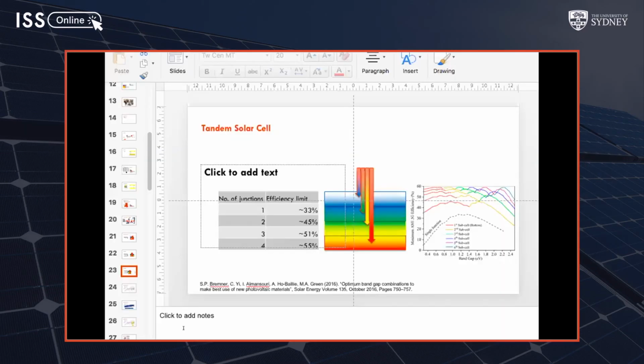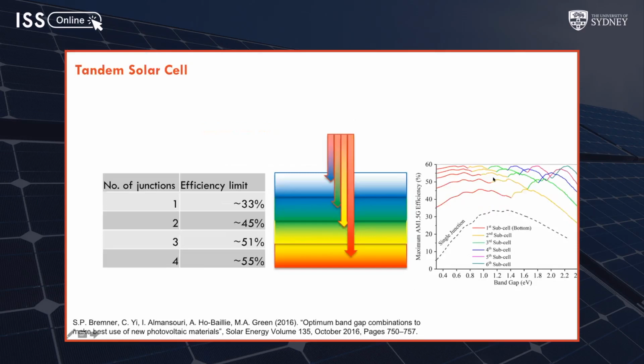Yeah, so if you remember, I showed that diagram where you can keep going, but the complexity outweighs the advantage. So if I can find it, I can find it. Good. Share screen. There. So you can see that there's lots of incentives of doing 2-junction, 3-junction, or 4-junction. But as you go up to 5-junction and 6-junction, I think the pain outweighs the gain, because every time you introduce an additional cell, you think you're introducing an extra layer, but it's not. Usually it introduces 4 to 6 additional layers, including the absorber material itself. And the integration is not as easy as you think. Integration is always the toughest thing to do. So I think, 4-junction, pretty much we can stop there.